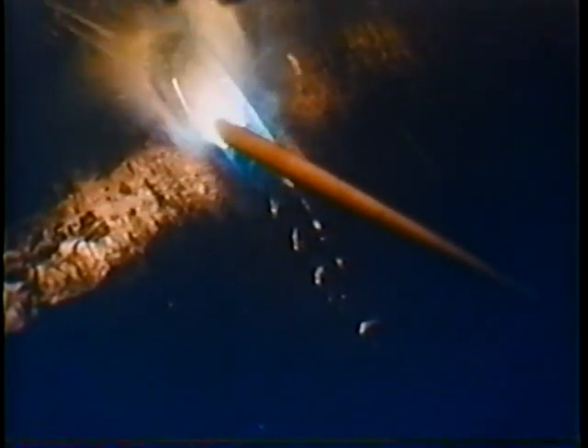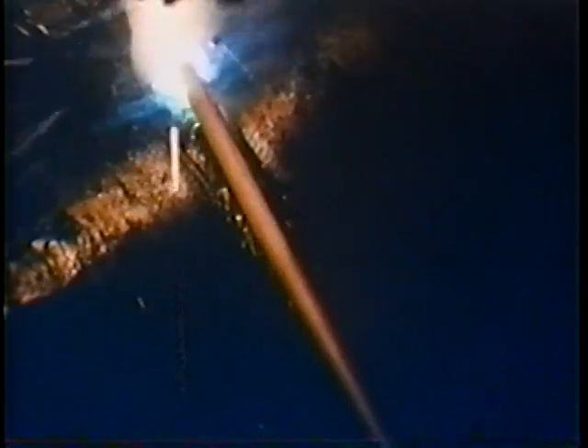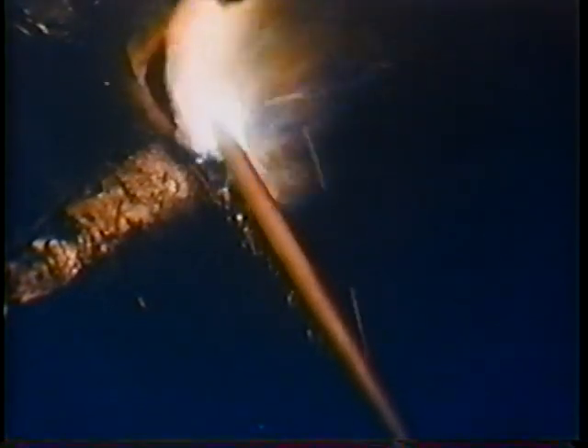The third pass is made along the lower side of our groove. This provides us a shelf on which we can place the fourth pass. Note how the toe of the weld laps over the pipe just a slight amount, and we have the proper fill. The fourth pass is placed on the upper side of the groove, properly filling this area. It must also lap over and fuse with the pipe and the previous bead.